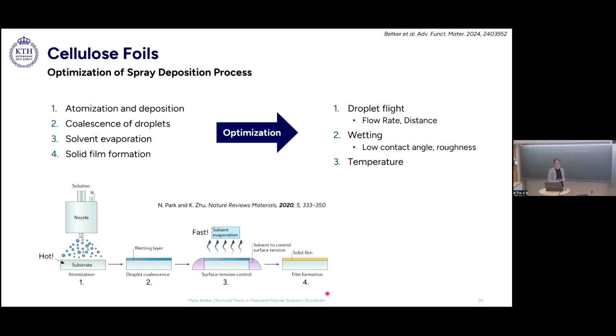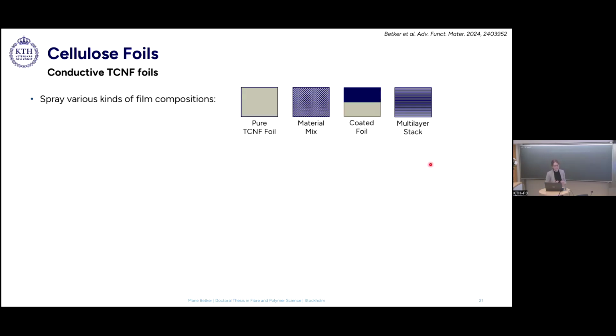And then I went into this process and optimized it by changing the droplet flight. Here you can change, for example, the flow rate or the distance. Then I optimized the wetting behavior by using silicon wafers and a special cleaning procedure. And in the last step, I also adjusted the temperature of the substrate. And by doing that, you can spray TEMPO cellulose.